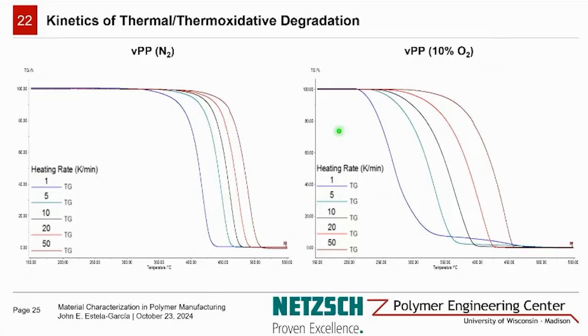When we're focusing on the oxidative data, we can again appreciate this secondary reaction during the slower heating rates. And once we reach 10 Kelvin, we no longer appreciate this. So the basis of a good kinetic analysis is having ample data at varying heating rates, which allows us to capture significant degradation events and thermal dependencies. We can also here appreciate how this looks like.